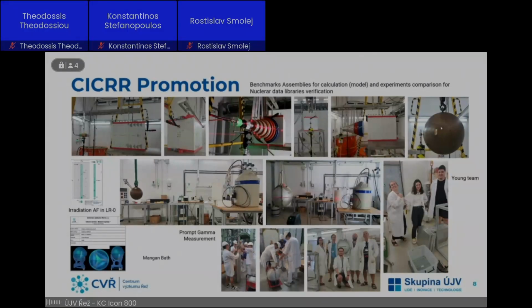You see already the iron sphere, which is now with a californium source inside as a reference standard or reference neutron and gamma field that could be used for the spectrometer calibration, for nuclear data verification, and other purposes. As you see this iron sphere, we have a nickel one. We have a heavy water sphere with a diameter of 50 centimeters, of course, light water and others. Also, we are able to measure the leakage spectra using the californium source at blocks of different material.